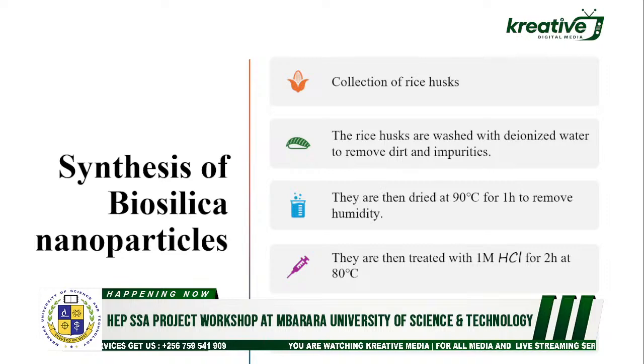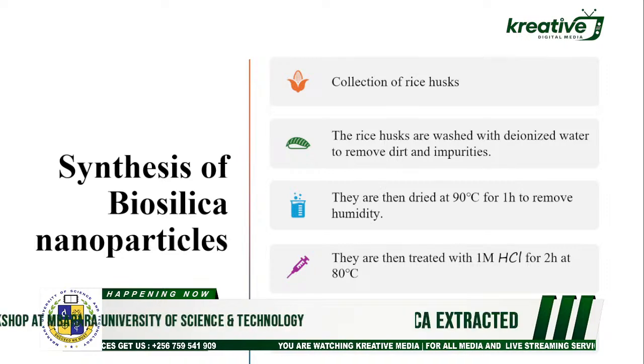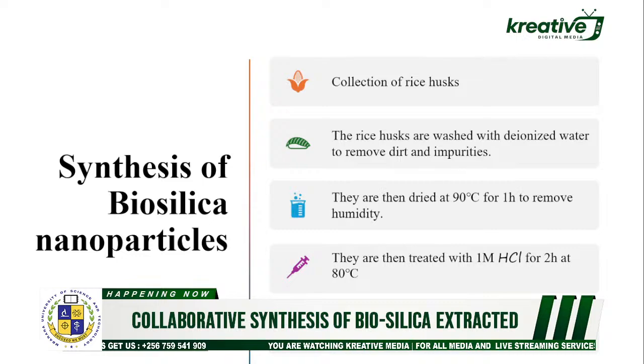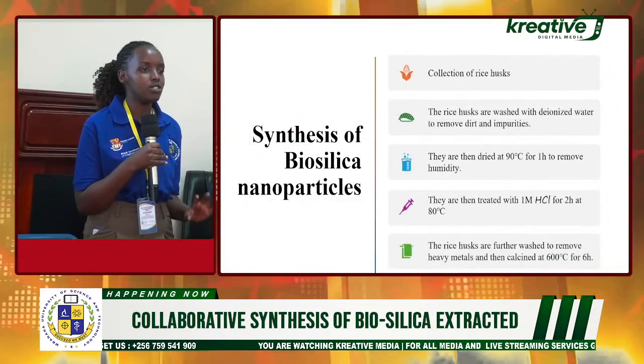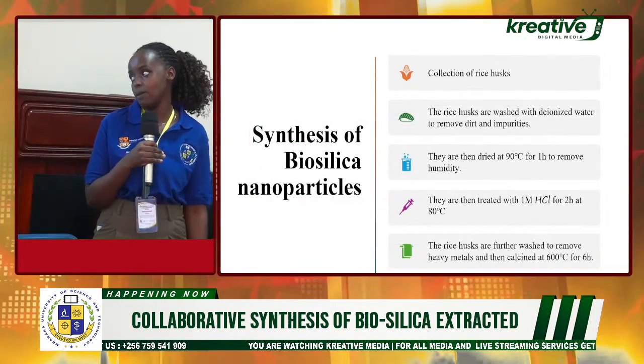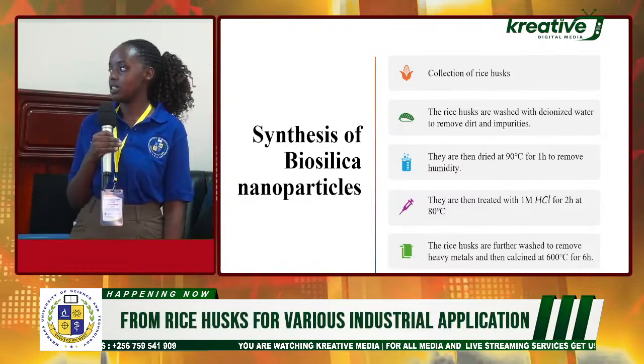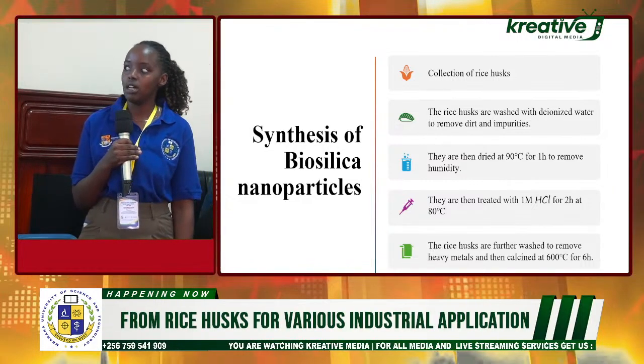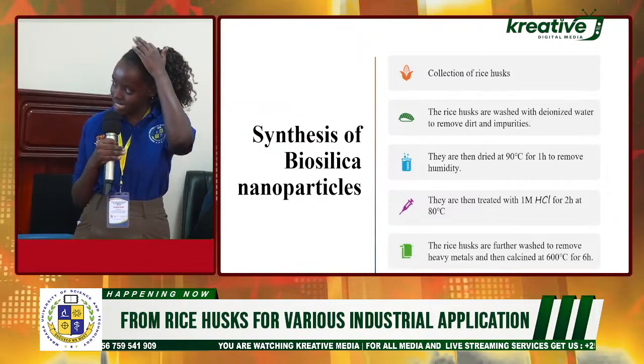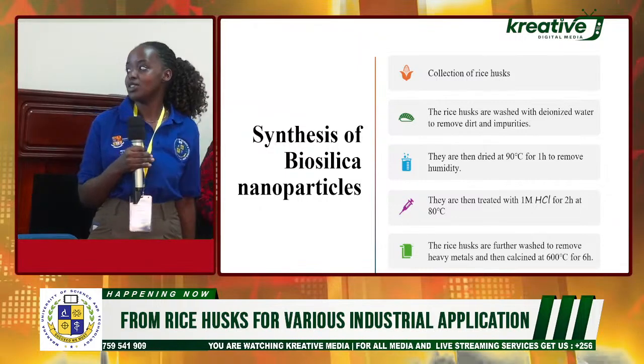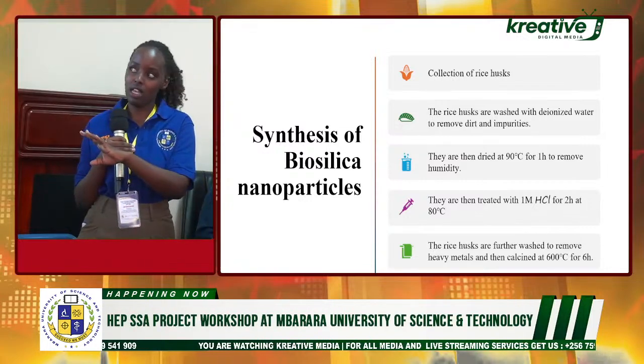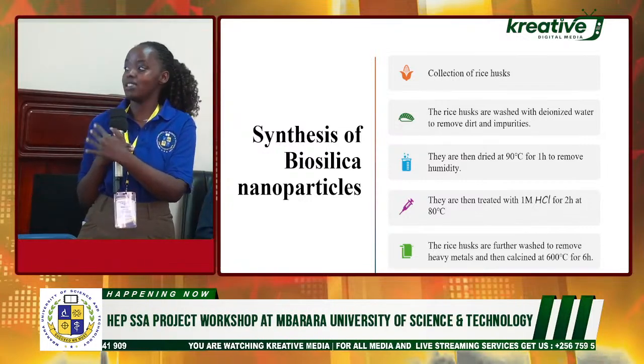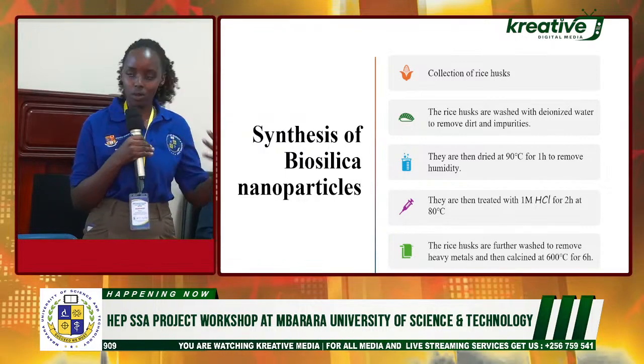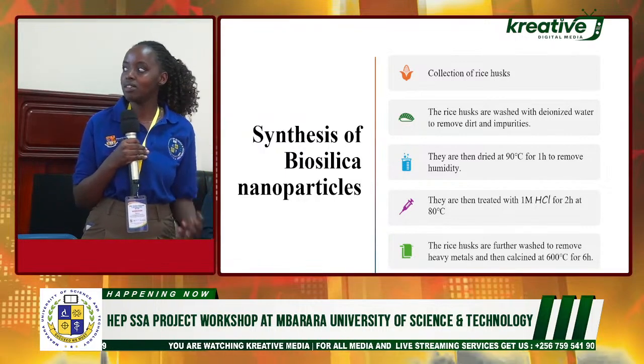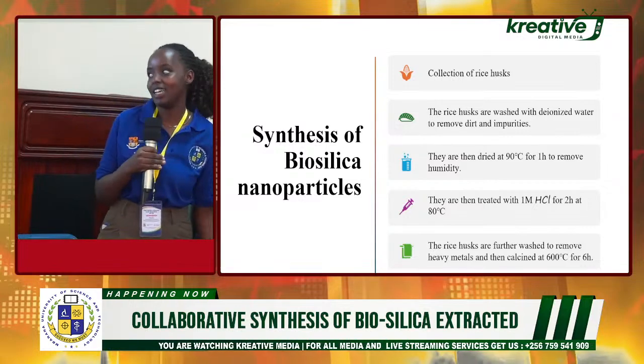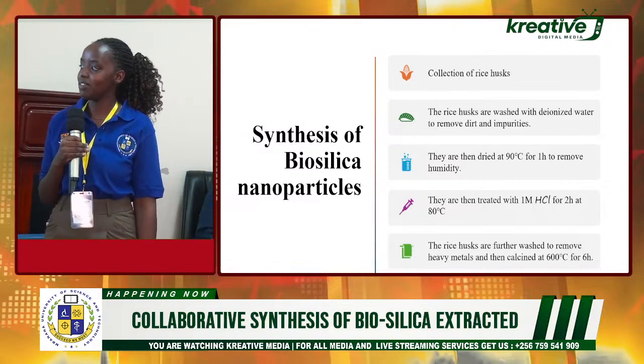And then we do calcination. Calcination is basically combustion in a controlled environment, usually in presence of a very limited supply of oxygen. And we are doing it at 600 degrees Celsius for 6 hours. And why 600 degrees Celsius? It was proved that this is the best temperature if you're to obtain the desirable size and type of nanoparticles.